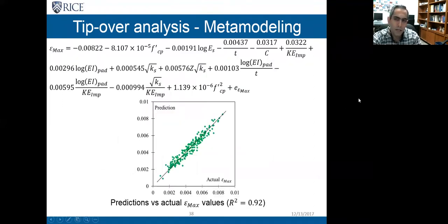In an impact scenario for the casks, one of the main concerns is that the cask maintains its integrity, and we do not want to see any release of radioactive material. For that, usually in the industry, the main concern is on the canister, and we don't want to see any fracture in the canister. To study that, we have developed a meta model for the maximum strain in the canister, which I show here, and how the model performs. I should mention that fortunately, we did not observe any fracture in the canister, but we observed many yielding cases. In fact, in almost all the cases, the canister yields, but it does not fracture, which is good news.